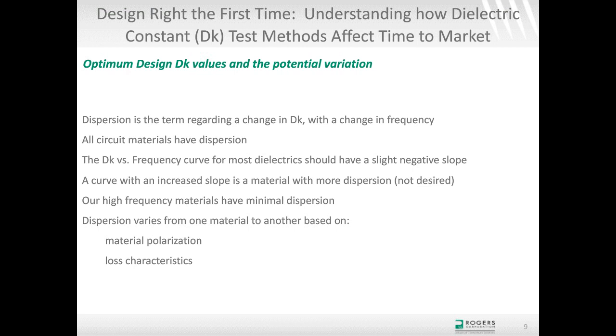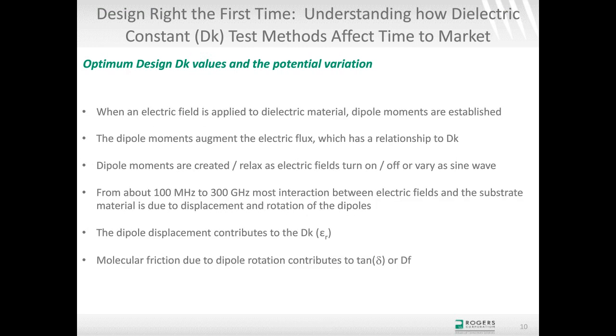And this dispersion is due to a few things. One is material polarization in a molecular sense, and then also loss characteristics. And how this works is when electric field is applied to a dielectric material, there are dipole moments that are established. And when the electric field is turned off, they relax. And when these fields are turned on and off faster and faster, they get to the point where they do not fully relax, and that dipole relaxation actually adds some energy to the electric flux, which relates to dielectric constant.